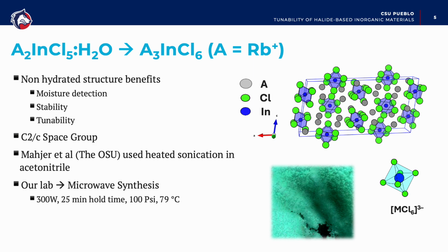We did spend a great deal of time and effort testing the correct combination of these parameters. And again, with respect to that space group, it was previously reported by Dr. Pat Woodward, and we confirmed that with our preliminary data. And we also confirmed that the antimony 3+ activator was vital for the green emission that you can see in this picture.